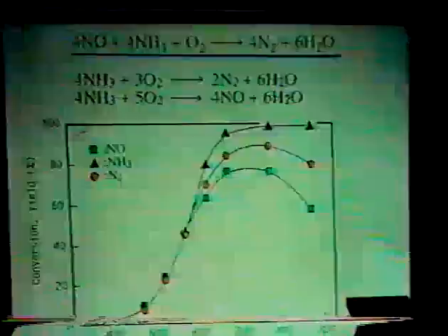At these temperatures, the activity and selectivity of these catalysts did not change, at least for 48 hours on stream. Reaction products containing nitrogen atom were nitrogen with trace amounts of NO2 and N2O. This figure shows the typical relationship between the reaction temperature and the catalytic activity. The conversion of NO, the conversion of ammonia, and the yield of N2, assuming this reaction stoichiometry, gave almost the same value at 573 K or lower temperature. These observations indicate that this reaction takes place selectively at lower temperatures.